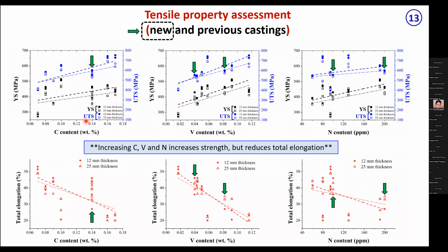So composition, as expected, increased with carbon, vanadium, and nitrogen. Nitrogen, of course, is very beneficial in vanadium-containing steels. As we have seen, even at low carbon level, we have got very good properties. But this time carbon went a little higher, and we are not getting that much benefit. In both steels, there was nitrogen of more than 190 ppm.